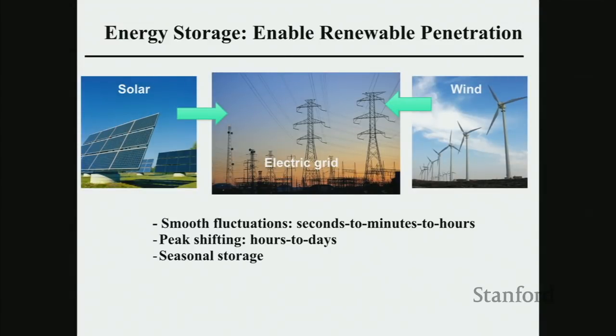And also seasonal storage. We have a lot of solar during the summertime, but not in the winter time. And certainly seasonal storage is a lot harder. The easier one to start with could be these seconds to minutes to hours. The more cycles of the battery you use, the better for the batteries in terms of the cost consideration. Seasonal storage, you use it about 1 to 2 cycles per year. So that's not a good use of your battery from the cost.